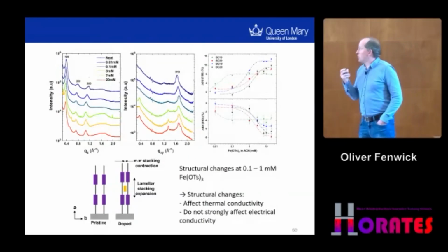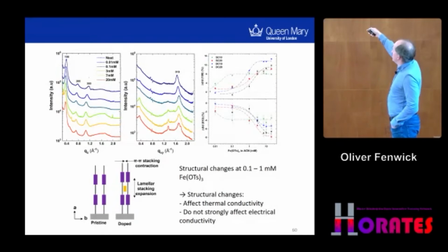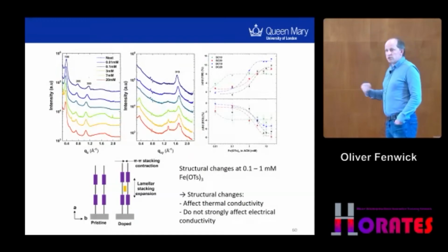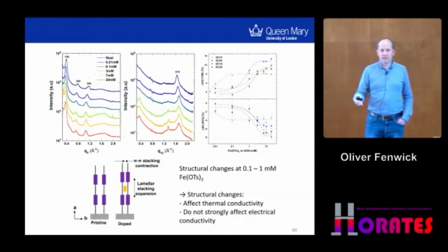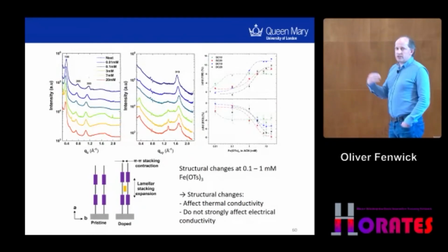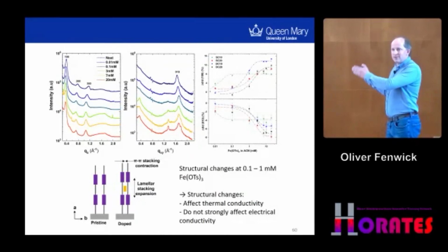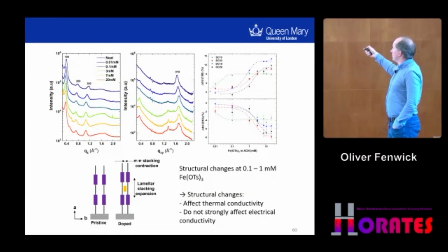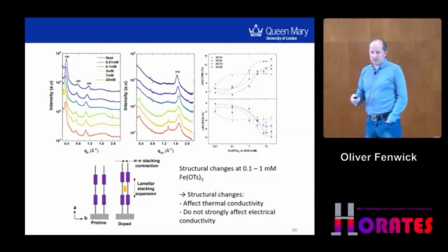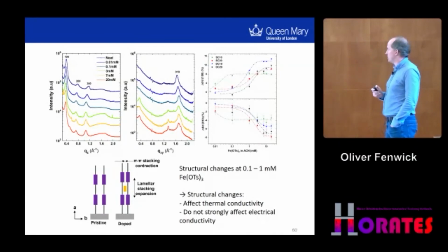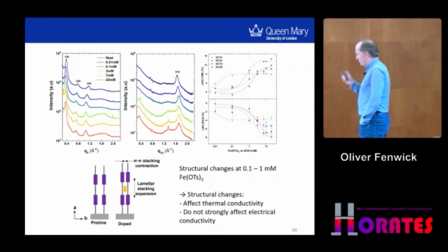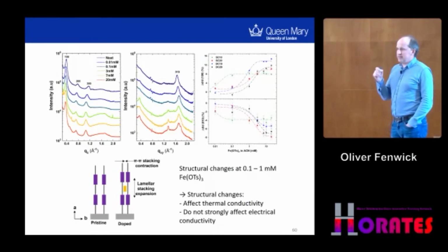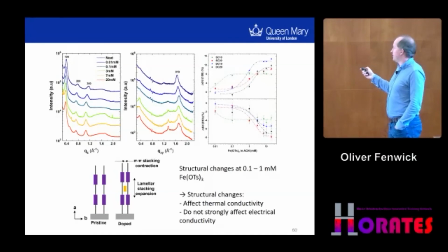If we look at the structural changes upon doping, without wanting to go into too much detail, we've got the change in lattice parameters on the right-hand side, and we got both the pi-pi stacking and the interlamellar stacking. We see that the lattice parameter also changes in the structure at very low doping levels, which is very much consistent with the change in the thermal conductivity, but not so well aligned with the change in electrical conductivity. So it seems that it's this structural change that is driving the increase in thermal conductivity, lattice thermal conductivity in P3HT at low doping concentrations. And I think that's an important message to leave with the polymers, which is that thermal conductivity isn't constant, and small amounts of doping can increase it quite a lot.